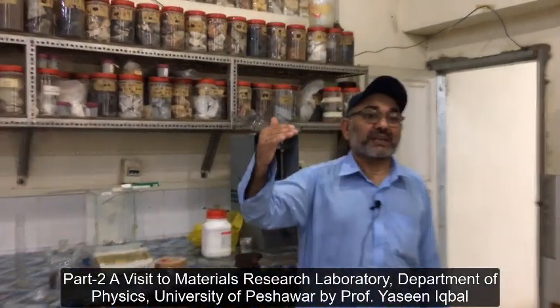This is a manual pellet press, we have one automatic pellet press. Internationally people use isostatic pellet presses. So there are various sorts of presses which densify and press powder to different densities. So you achieve, for example, 40% dense material when you press it with the optimum pressure. Now, for microwave dielectric application, for example, you need above 95% dense material.